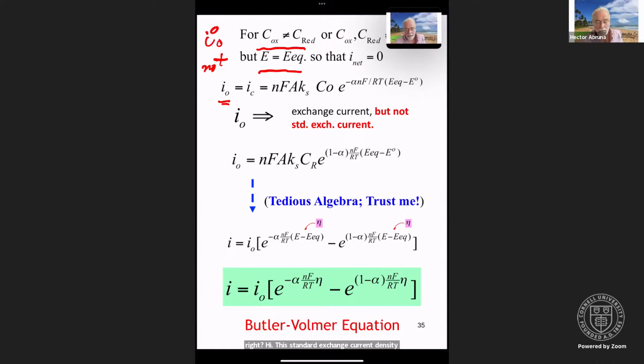So if we have a one electron process and we have ox and red, if we change the ratio of ox and red by a factor of 10, and we change the potential by 59 millivolts, we can still be at equilibrium, but at a different potential. And so at that potential, the exchange current density will be different from the standard one. Nevertheless, we can express the exchange current density with I cathodic or I anodic, because they're going to be the same: n F A Ks C0 e to the minus alpha, like we had before. And as I mentioned, this is the exchange current density, but not the standard exchange current density, because we are not at the standard potential. And so we have this expression that comes from here.